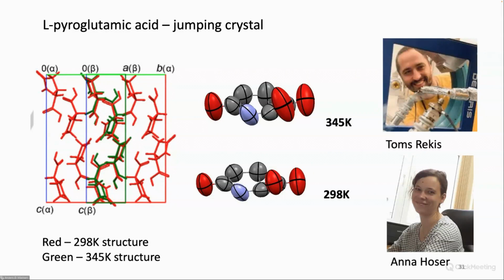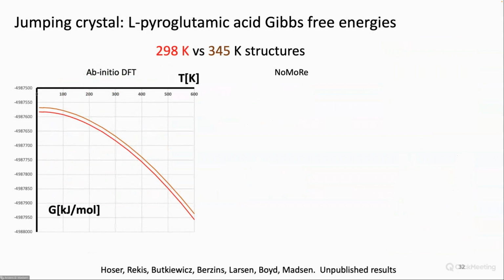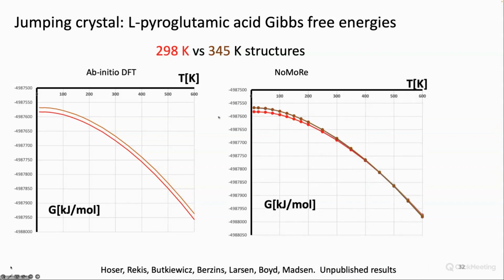But we were interested in looking at, again with this normal mode refinement, can we say something about this phase transformation, about the thermodynamics of this phase transformation? And actually, we can. If we only use the DFT calculations, these free energy curves where we sum up all the different contributions to the free energy do not cross, so it looks like a monotropic system. But if we use the normal mode refinement approach, then we have a crossing of the two free energy curves for these systems at a fairly reasonable temperature, close to what we would expect, or what we observe experimentally as the phase transformation temperature. So that is quite encouraging for the accuracy of our approach here.